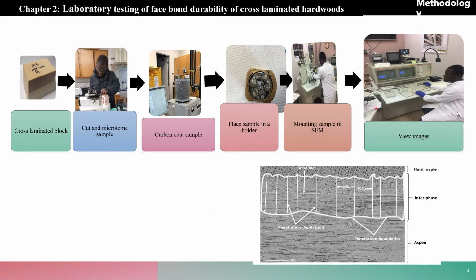We also subjected the bond line to analysis using a scanning electron microscope. So the scanning electron microscope images were taken from a 10 by 10 millimeter square cut from the center of each cross lamination with the bond line placed at the center at 39 millimeter working distance. The accelerating voltage was 15 kilovolt under 3 different magnifications, which are 300, 200, and 100, using the JEOL 6400 SEM with tungsten source scanning electron microscope.